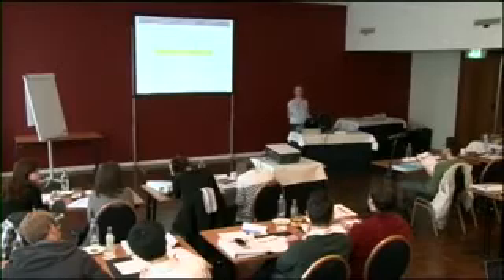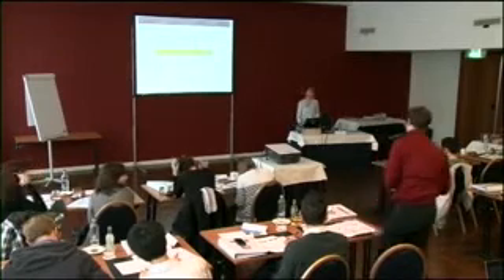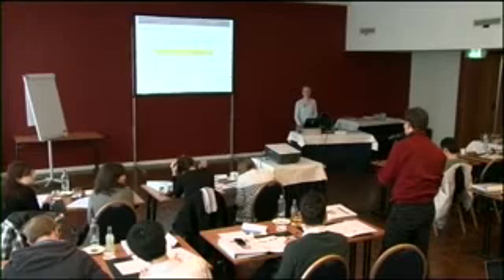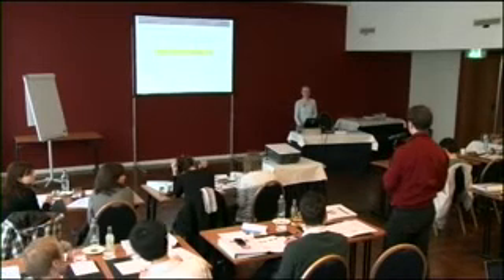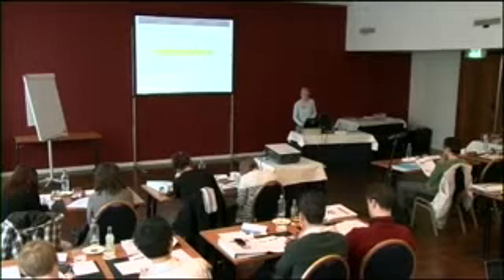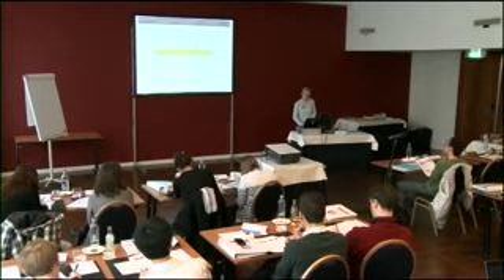Yeah. Okay. Please. Yes, can one associate a pore size scale with the temperature scale? Yes. You have the Gibbs-Thomson equation where you can translate, making some assumptions again, the temperature to a pore size. And that's done. And with the Gibbs-Thomson equation, at high temperatures, small changes in temperature have a huge impact on the calculated pore size, whereas at lower temperatures, it's more robust. Yeah.